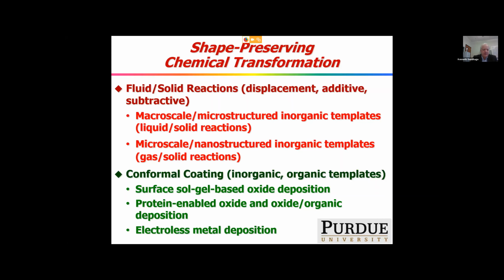Now, I should confess that in this case, the replication we do is actually negative. In the case above, we're making positive replicas from a starting material. In the cases below on conformal coating, they're actually negative replicas. We're putting highly conformal coatings on a complicated shaped template and then removing the template. So the coating is where there wasn't anything previously, so it's really a negative coating. But if the coating is conformal and thin, it appears as though it's a positive replica.